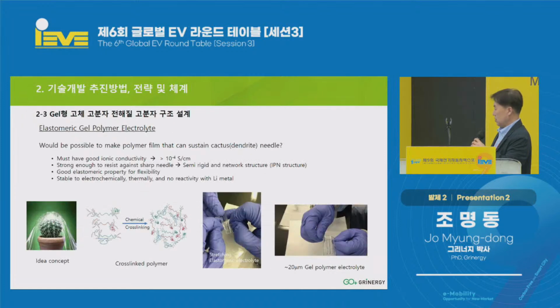The dendrite, the shape, the idea that we got is just like a cactus. And just covering it with the film, it does not break out. So if we create a film, then we can sustain the dendrite. So this was the idea that we started with, and in order to come up with this, the cross-linking system is what we need. So we have introduced the chemical cross-linking, and then we came up with 10 to the minus 3,